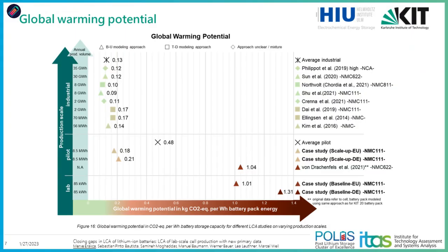We conducted sensitivity analysis to address uncertainties and to analyze potential effects of scaling up production to pilot scale. As expected, increasing the throughput of cells in the dry room and reducing loss rates would lead to a drastic reduction of the environmental profile. We could see a six-fold difference in climate change impact between our lab-scale production and the upscaled pilot-scale battery pack production, confirming that production scale and throughput have a massive impact on the environmental profile of batteries produced.